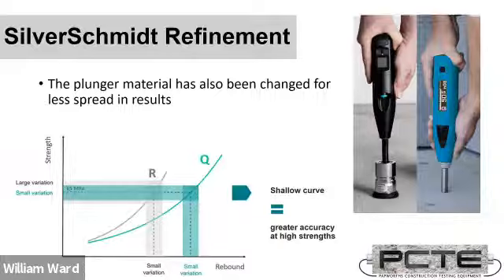Something that you do need to be mindful of, which might affect a Schmidt hammer measurement, would be the overall thickness and stability of the concrete. When you conduct a Schmidt hammer test, your concrete should return as much energy as it can to the hammer. So if you're testing something like a cylinder, and that cylinder is able to roll or move under the impact, the rebound will be weak, and you will underestimate strength or record a lower raw unit than is correct. So this is why we use Type L hammers for very thin concrete. The other big factor that can affect the quality of your test is the surface finish. So if you have a rough surface finish, even something as normal as a brushed surface finish, which is also a worked area of the concrete, which may have an inherent reduction, you need to smooth that down to bare,